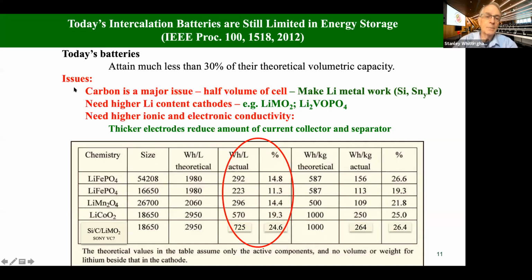To do that, we have to do a number of things. One is we have to get rid of most of the carbon. So I mentioned a moment ago, it takes up half the volume of the cell. So we either need to make lithium metal work, or in the interim, make silicon or tin work. In addition, we need to use all the lithium in the materials. In these layered oxides, we use about 60% at the moment.